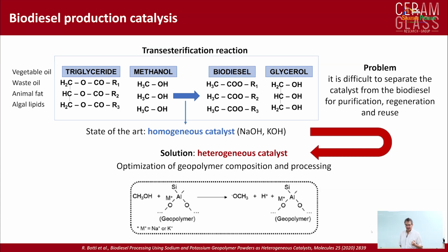The problem with this approach, which is the normal one, is that it is difficult to separate the catalyst from the biodiesel for purification. You need to wash the biodiesel several times in order to reduce the content of sodium hydroxide below a certain level. So we thought that we could use the geopolymers, since they provide a very high pH, as a heterogeneous catalyst, with the advantage that you can simply remove the solid from the liquid and you have no separation problems.